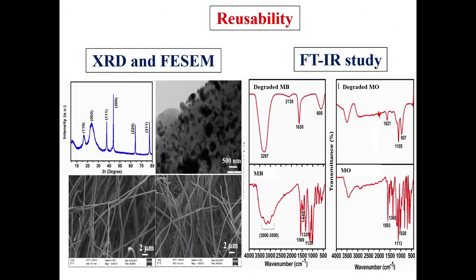In the reusability study, with the help of XRD and FESEM, there is no change in the structure at all. The peaks of XRD remain the same, showing that the decoration of silver graphene sheet remains as such over the surface of the PAN. No change in the thickness, no change in the porosity of the particle, only a minor change over the structure of the particle. We have done the FTIR study of degraded MB, that is methylene blue, versus pure methylene blue.